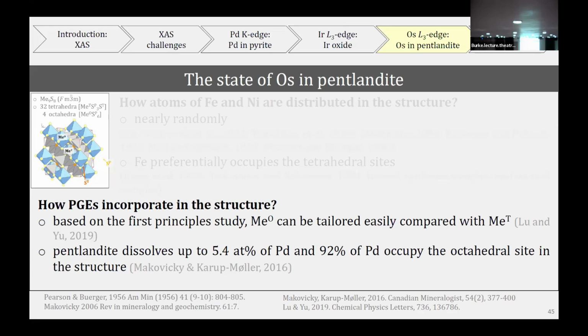But here, on the slide, I put two things which I would say could give us a hint that the position where osmium incorporates could be octahedral. The octahedral positions are more flexible in terms of moving the cations. And also Makovicky and Karup-Møller proved that almost all the palladium that they managed to dissolve in pentlandite was in the octahedral sites.